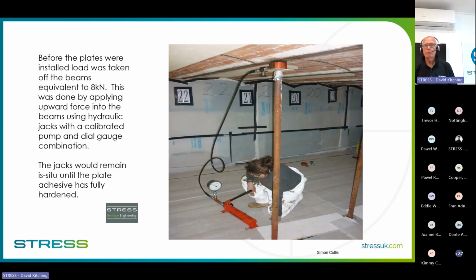And before we started putting the carbon fiber on, we actually jacked some of the load out of the cast iron. Now, you can't do very much jacking because remember it's stiff and brittle. So we were only putting about 8 kilonewtons into each of the jacks. But what that did was just take some of the load out and lift the center of the balcony by only a couple of millimeters. That meant that after we'd bonded the carbon fiber to it and we took the jacks out, it will immediately put some tension into the carbon fiber, which then is helping the cast iron.